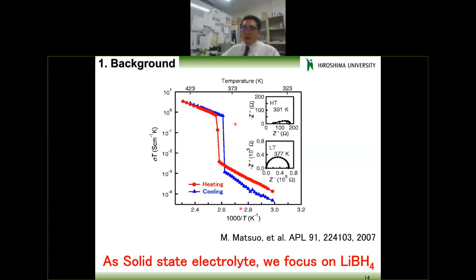And there is one quite typical structural transformation at about 115 degrees C. This axis is inverse temperature, and this is ionic conductivity. As the temperature increases, after that structural phase transformation, this material shows quite nice superionic conductivity. So they focus, or we focus, on this material as a solid electrolyte for the lithium-ion battery. So that is the background. It's slightly long.